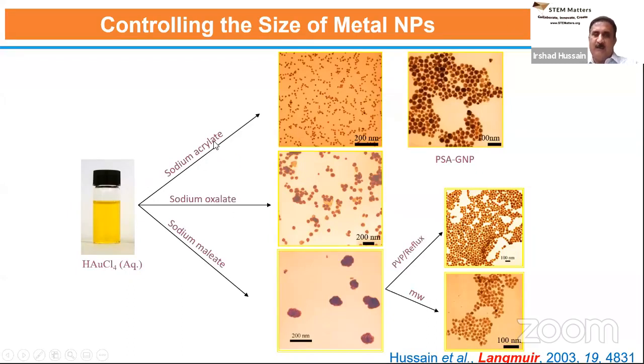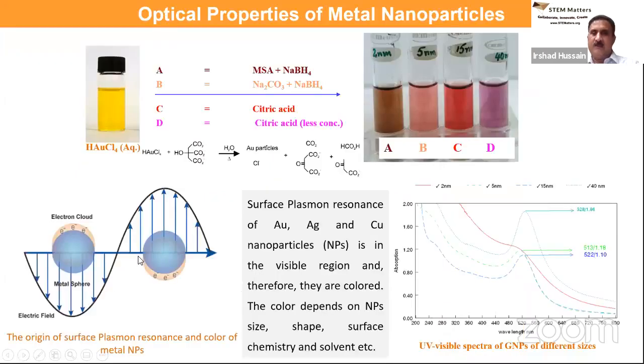For example, these acrylate stabilized particles are very similar to citrate stabilized gold particles, and their size is about 15 nanometer. They are extremely red in color, and they absorb at about 520 nanometer. But if you increase their size, there is a red shift in the absorption. The color of these particles is due to surface plasmon resonance bands that we can discuss. Here you can see that by using 4 different strategies, you can prepare gold particles of different sizes. You can see different colors, and these colors mean that these are particles of different sizes. Initially, the brown color, for example, is 2 nanometer or even smaller, and they don't have any surface plasmon resonance band.